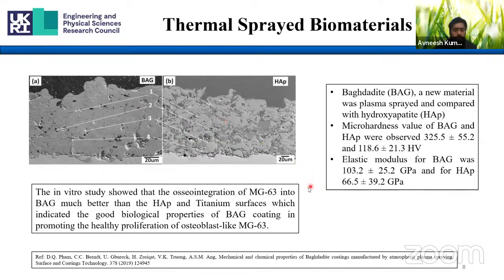Similarly, they have also conducted some biological testing. They seeded osteoblastic MG63 cell culture over these surfaces and found that bagdadite was able to promote the proliferation of the osteoblastic cells in that environment. So basically, this bagdadite has shown better biological bioactivity or biological performance when compared with the hydroxyapatite surfaces or titanium surfaces. Then the main problem with these thermal spray coatings is the high temperature.